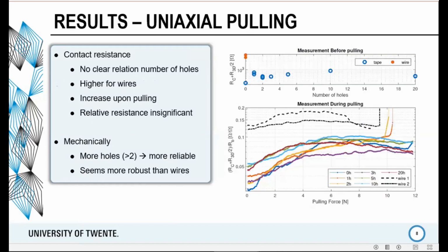So for the results, we measured the contact resistance before pulling on a sample, and there we saw that the number of holes doesn't really seem to influence the initial contact resistance. Although for the copper tape, our contact resistance was significantly lower than for the embedded wires.